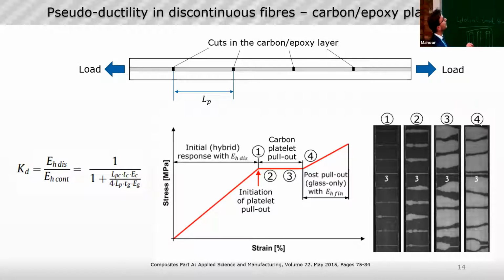So we have a kind of sandwich where the external plies are the glass layers. In the middle we have this continuous layer of carbon. The carbon is pre-cut. So we have these discontinuities, and the aim is to trigger delamination. In fact, in a tensile test, we see that delamination starts propagating from the cuts, and it continues. And as soon as this strain interval ends, it gets a kind of saturation. And at the end, in the last stage, we have the pull-out of the glass solely.